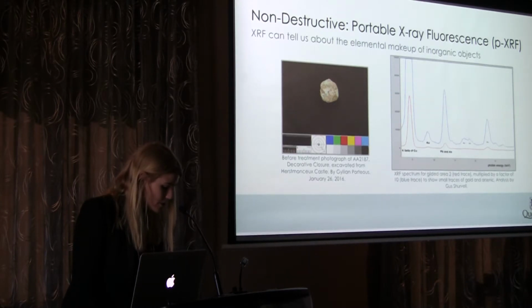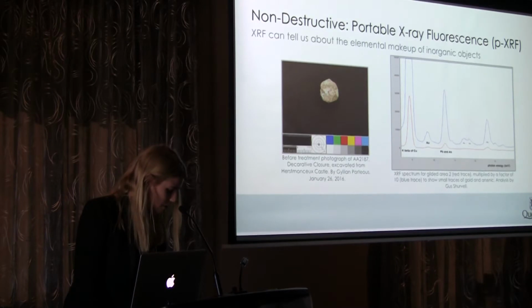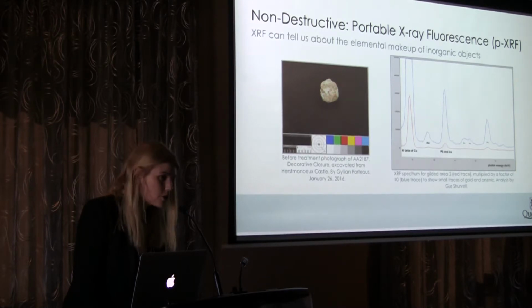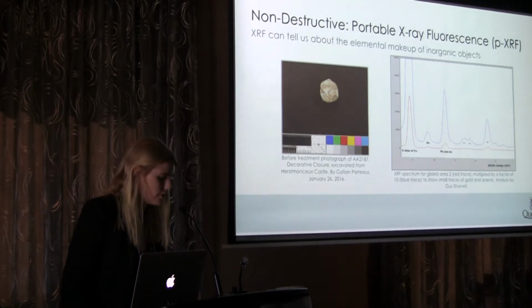The archaeologists brought the decorative closure to the MAC program for treatment and analysis. As the object displayed evidence of what appeared to be gilding, we were able to confirm the presence of gold, in addition to arsenic, possibly a component of the gold mixture itself, through the use of XRF. The gold leaf is so fragile, this information not only greatly changes our treatment approach, but adds to the information for the archaeological record.